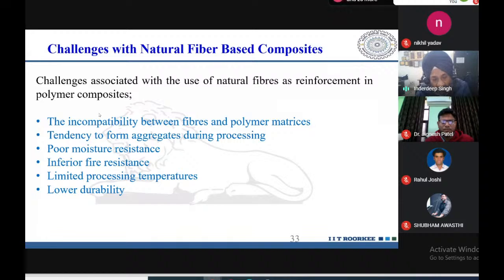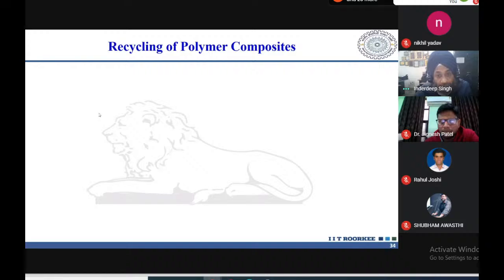Also, the durability is important, because mostly in the rainy season we see that the wooden doors normally have a tendency to swell because of absorption of the moisture by the fibers. Therefore, the durability also needs to be ensured, that how these natural fiber-based materials can sustain longer lifespans. So these are some of the hints which can be taken by the researchers towards the research efforts in the field of development, characterization, and establishing commercial viability of natural fiber-based materials.